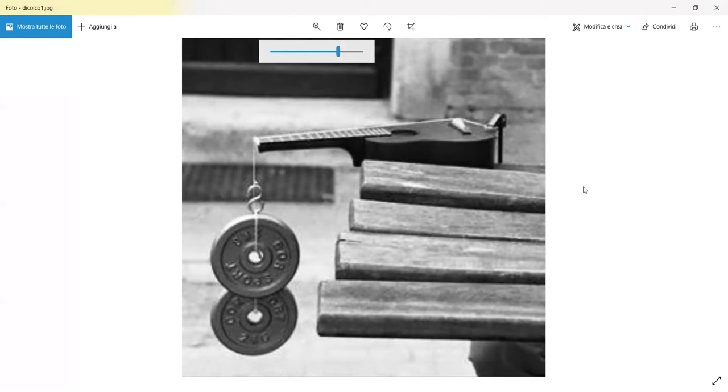To compensate for this, we should not start from 61 millimeters, I mean, by calculation, a full octave, but the first string should have a thicker diameter. The right proportion is 66. When I put 66 and 1.2 millimeters under the same weight, the 66 drops to 60, and the 1.2 drops by nothing because the stretch is there. So we have exactly the balance, the full octave.